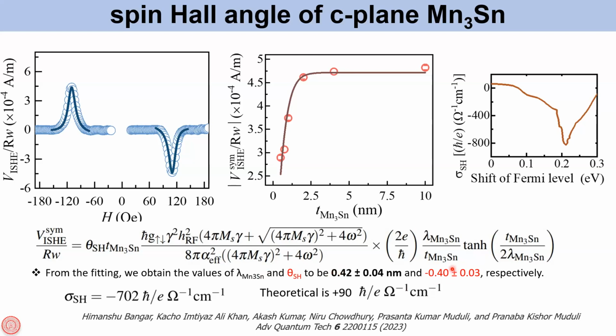But the spin Hall angle is found to be, first of all, negative, and it's quite large compared to what has been reported in the past for polycrystalline and nanocrystalline films. The theoretical value, however, is positive and is around this value. Our value is negative, and we explain this on the basis of a shift of the Fermi level in the actual sample, which can lead to the sign change and an increase in the magnitude of the spin Hall conductivity.